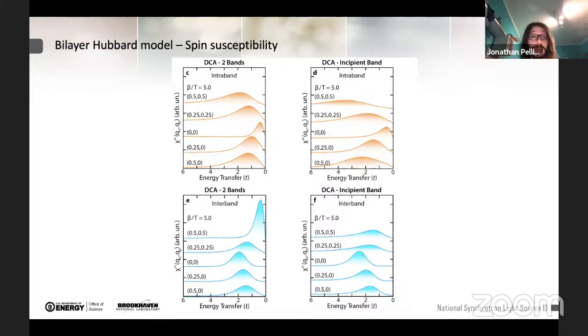Additionally, in this model, it is important to disentangle between what is called intraband and interband susceptibility, because the Kz can be taken as zero or pi. And here I'm presenting the results for these spin susceptibilities for the two-band model, plotted on the left-hand side, and for the incipient band case, plotted here on the right-hand side.